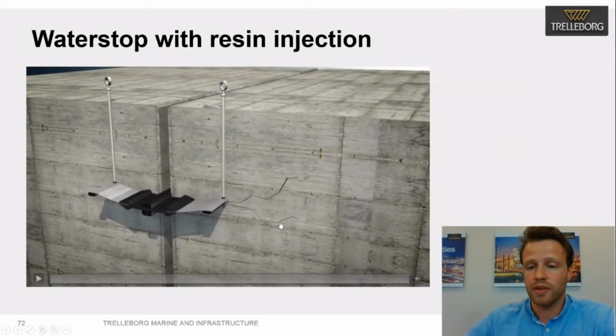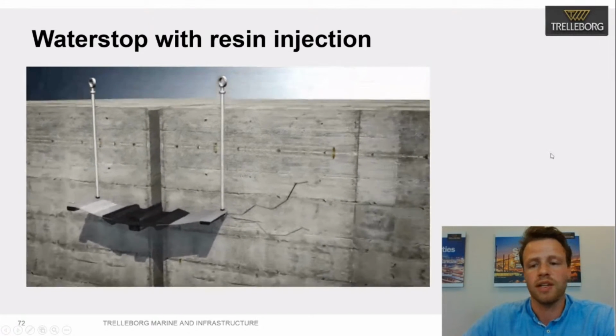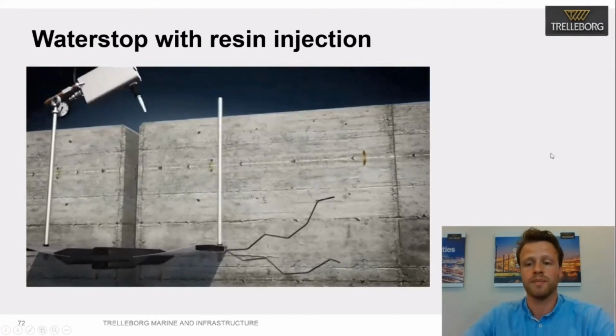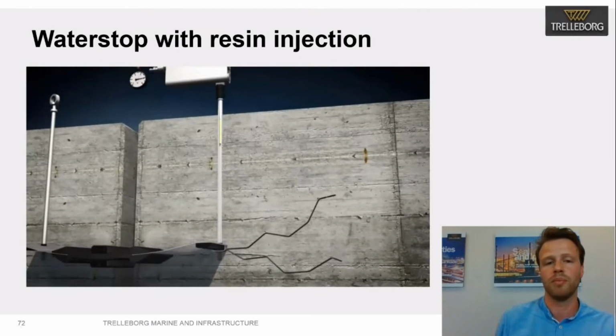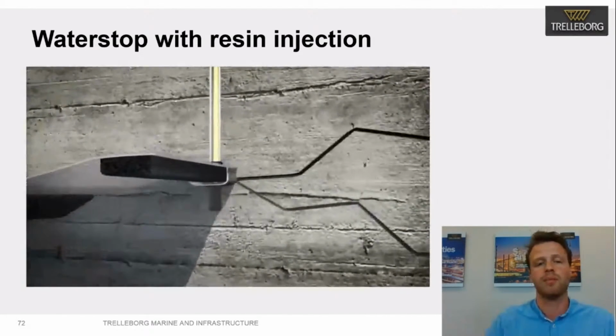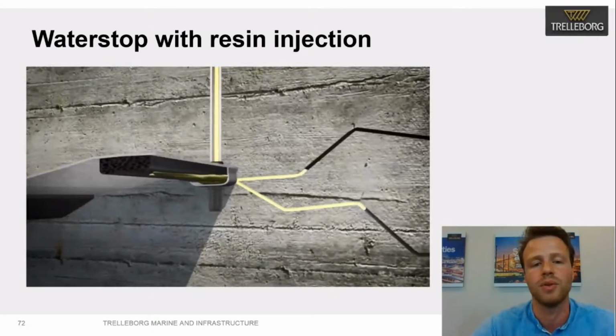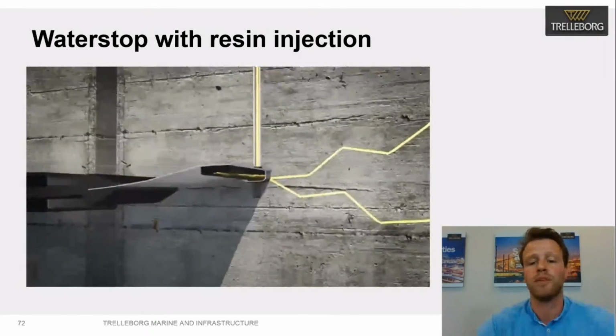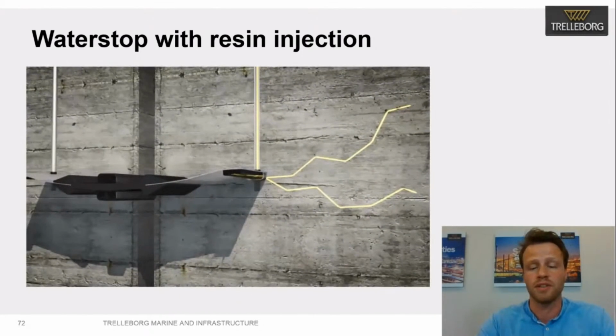There is a solution to make sure air entrapment and cracks do not affect your Waterstop that much. Here you can see the injection system with resin. What happens is that you pump an amount of resin into your Waterstop at 10 bars, and that resin flow will follow the path of least resistance, and thus fills up the cavities that can occur.